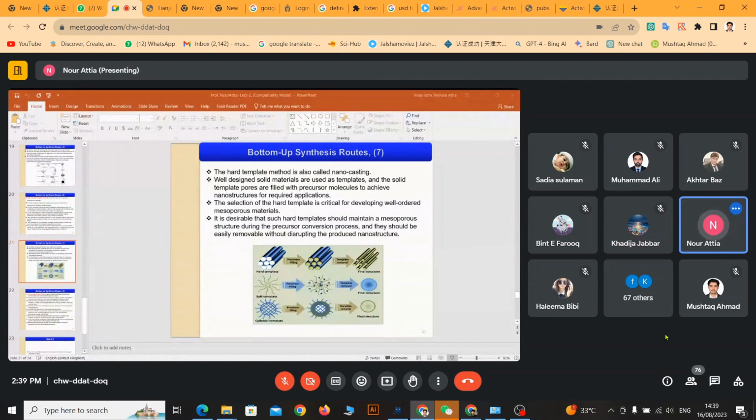Even though I was using it before to prepare some nanoporous carbon, recently I have been using carbonization activation directly, because you have to sacrifice the template, and the template also costs, and you need to reduce the cost of the material. Also, you are limited by the surface structures of the template. But if you are preparing other materials, then the optimization is open for you.